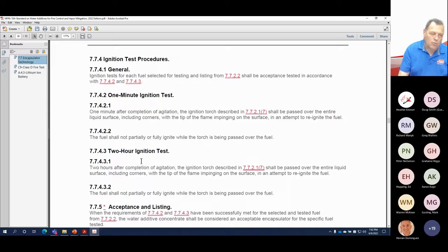So at first blush, people think that, oh, this is a fuel neutralization test. No, we're using the fuel to demonstrate, does this agent create spherical micelles? Are those spherical micelles capable of encapsulating this fuel? And is that encapsulation stable in the presence of high heat over an extended period of time? Hence a 1 minute and 2 hour ignition test.